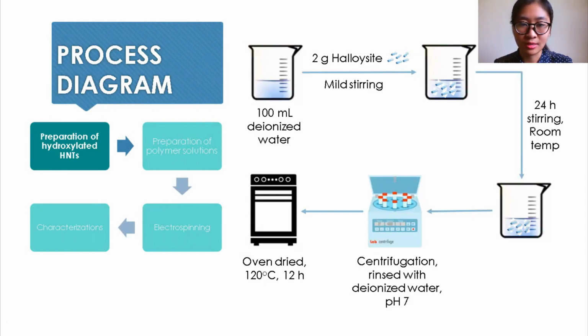reactive silanol groups. The resultant HNT solid phase was separated by centrifugation and rinsed several times with deionized water until pH was 7. The prepared HHNTs were dried at 120 degrees Celsius in an oven for 12 hours and stored in a desiccator until it was used.